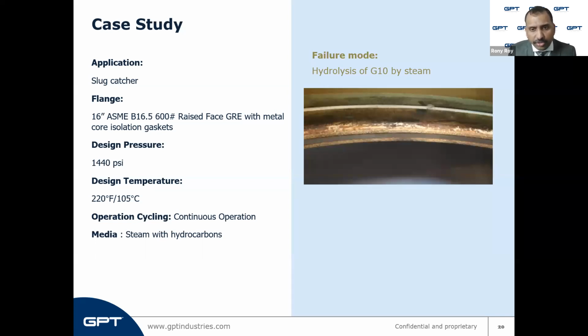In this case, the evacuation of the epoxy left voids in the body of the gasket. The voids were subsequently replaced by contaminants in the media stream, and that led to conduction and caused loss of isolating properties also.